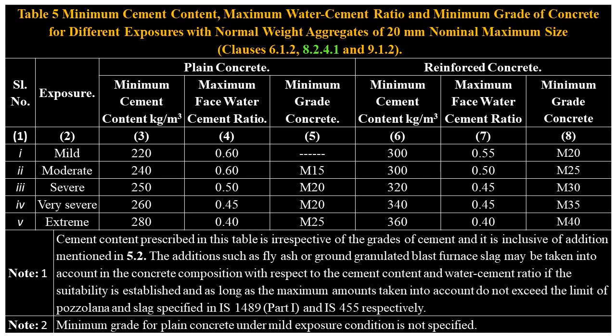referencing clauses 6.1.2, 8.2.4.1, and 9.1.2. Table 5 comprises 4 main columns and 5 rows. The first column serves as a serial number identifier, while the second column delineates exposure conditions. Moving to the third column, it addresses plain concrete, further subdivided into 3 subcolumns. These subcolumns detail the minimum cement content, in kilograms per cubic meter, the maximum free water to cement ratio, and the minimum grade of concrete required.